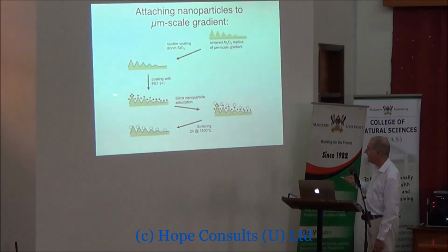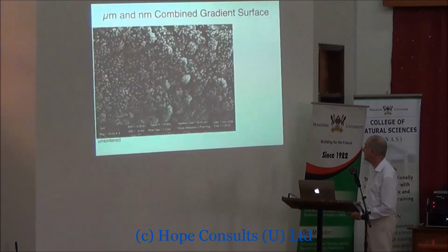We put the PEI on it again to make it positively charged. And then we dipped it orthogonal to the microscale gradient. We dipped it into the nanoparticles. They stuck on the surface in the gradient. We sintered it, and then we had our orthogonal nanometer and micrometer scale roughness gradient.